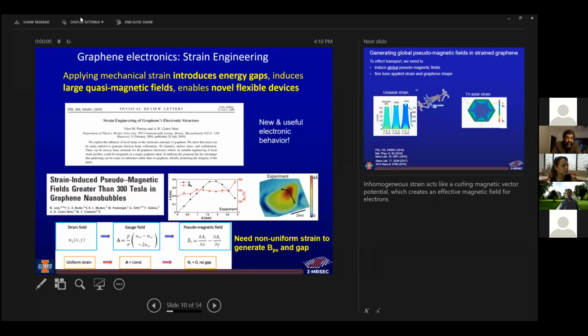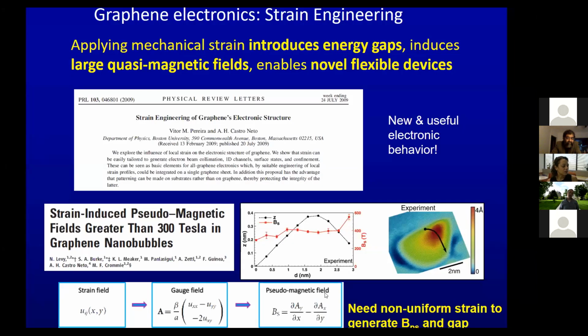Let me, maybe this doesn't make sense. I put this in a very small thing, right? So if you look at the very bottom here, this is specifically for pseudo-magnetic fields, but it assumes a non-uniform strain field, right? And then to get the pseudo-magnetic field, you basically have to take a gradient of that. So it's not the gradient of the strain, it is actually the strain field that matters. This is just a strain field directly as a function, not a gradient strain field. And that strain field itself goes directly into the vector potential. So all that matters is that you have the strain field.